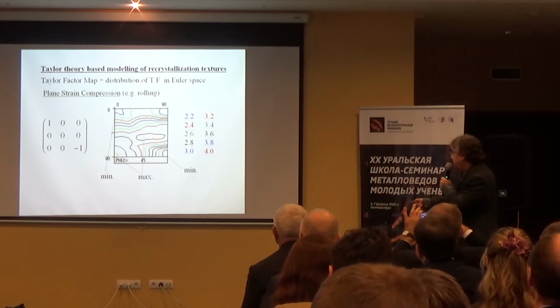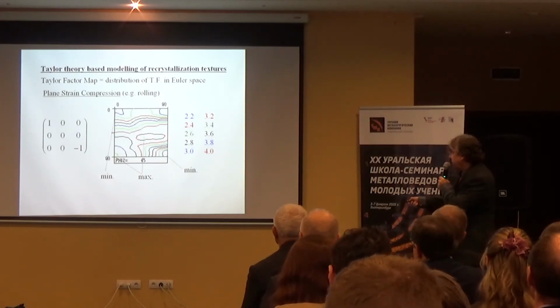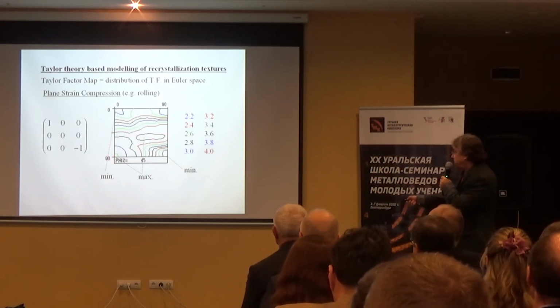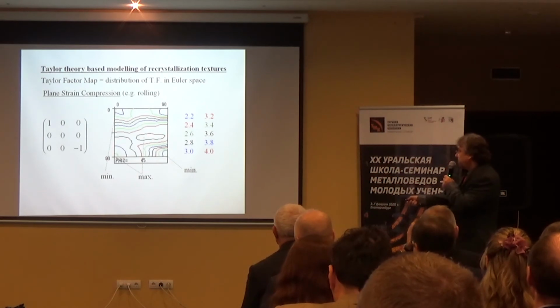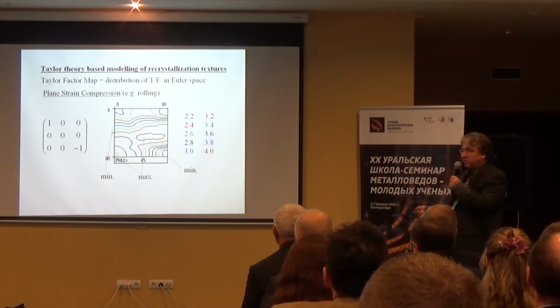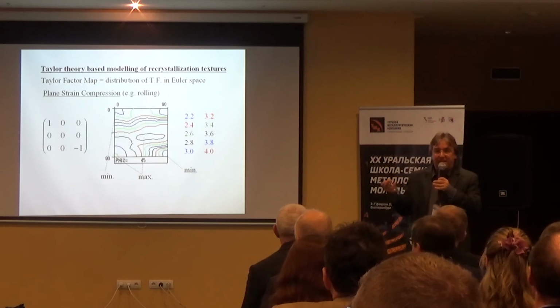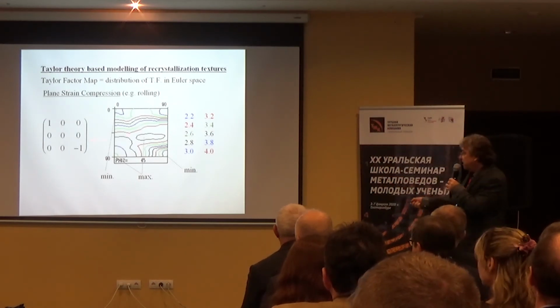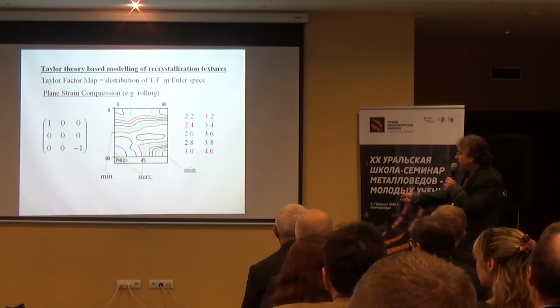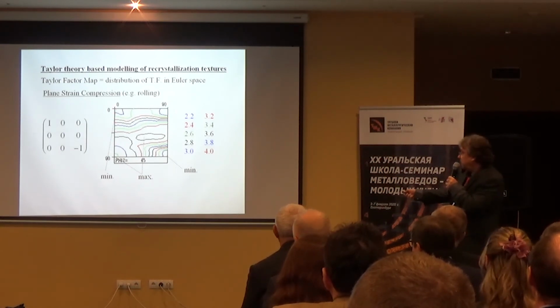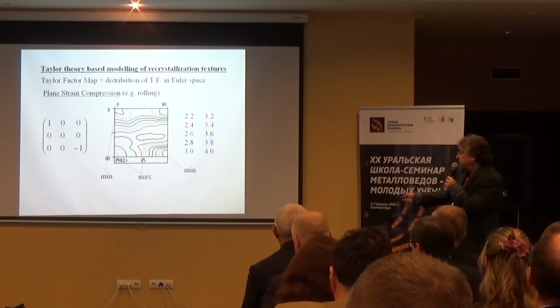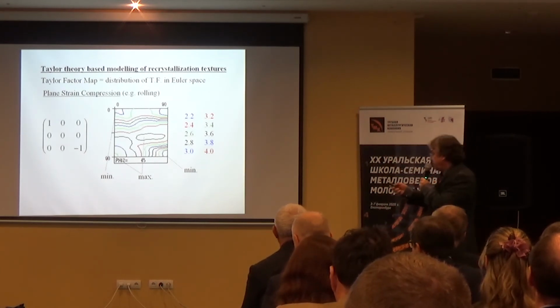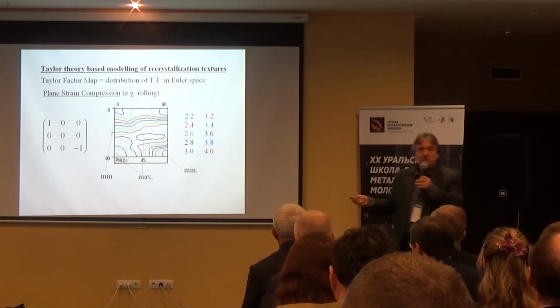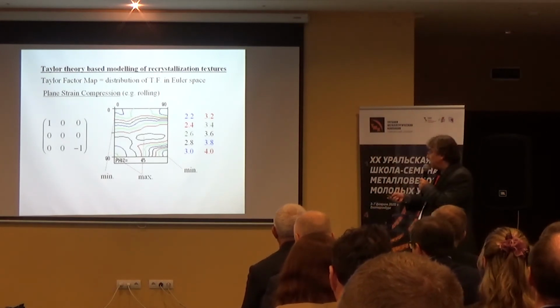You can see here that we have a maximum. So in this region, we have high Taylor factors on the gamma fiber. Do you see the correspondence with the experimental data, that these are high CAM value orientations? And here we have low Taylor factor values. It goes down to 2.2. This is minimum and this is maximum. So this is a theoretical calculation of the stored energy.